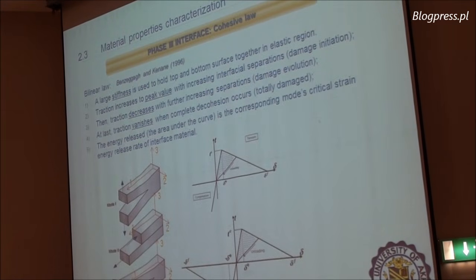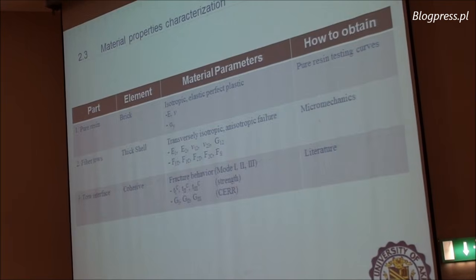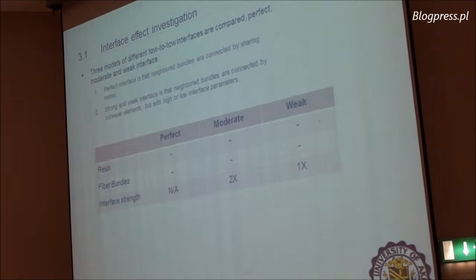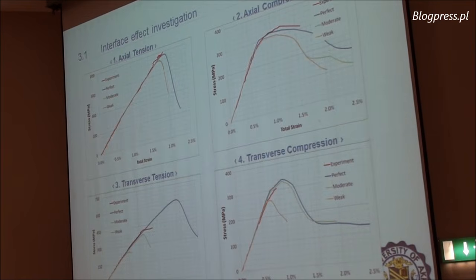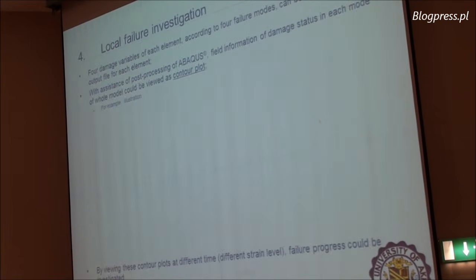to the model with the cohesive element used to measure the strength of the interface. And of course, those people who understand fracture mechanics know mode 1, mode 2, mode 3, and they are all captured in the cohesive element. And the bottom line is that you have a significant number of parameters you can adjust to make sure that the simulation, as you can see here, for the axial tension, transverse tension, axial compression, and transverse compression will capture the experiment as measured in the laboratory.